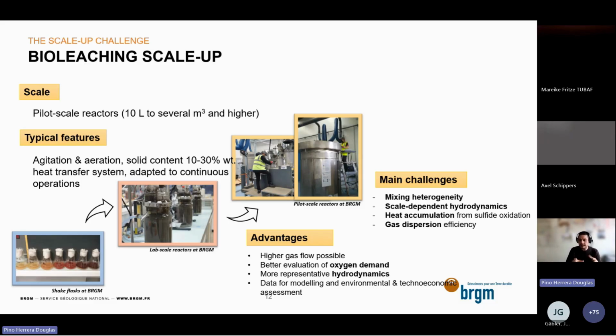This is the scale we usually use to obtain data for modeling, for environmental assessment, techno-economic assessment, and these kinds of necessary steps in the industrialization of a process. The challenges are that as we increase the system, we probably increase the heterogeneity of the mixing and of the gas dispersion. So this might be a little bit tricky and we need to be careful. It doesn't mean that because small scale works very well, a bigger scale will too. We have to be careful that all the parameters follow the correct path to a bigger scale.